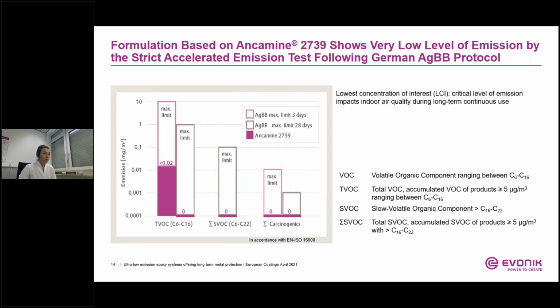So, a formulation based on Ancamine 2739, which has a very low level of plasticizer, shows a very low level of emission. And there are different ways to measure the emission. Within the European Union, you will find different directives for VOC control. One of the national regulations is from Germany, called AgBB, which sets quality standards for emission levels. Based on the concept of lowest concentration of interest, the AgBB committee has set the interpretation scheme. And this validates the accumulated emission at 3, 7, and 28 days after applying a coating in indoor applications.